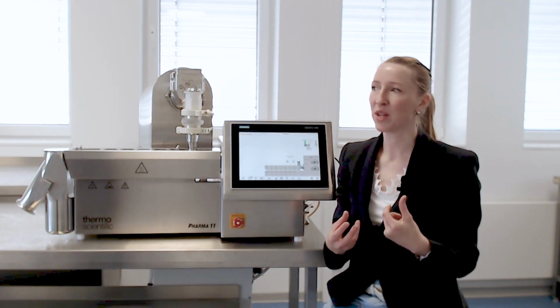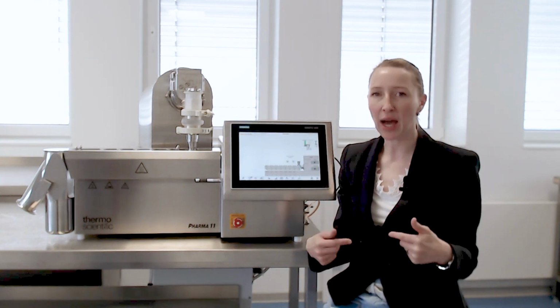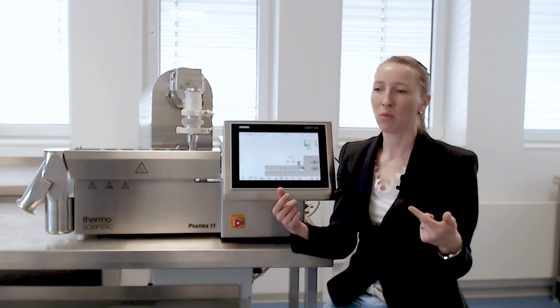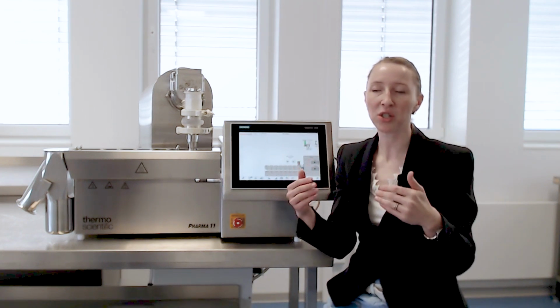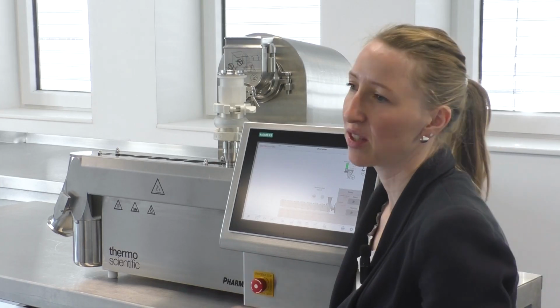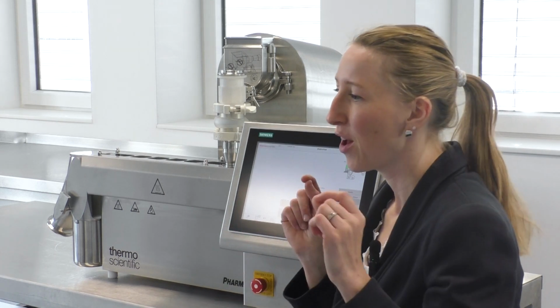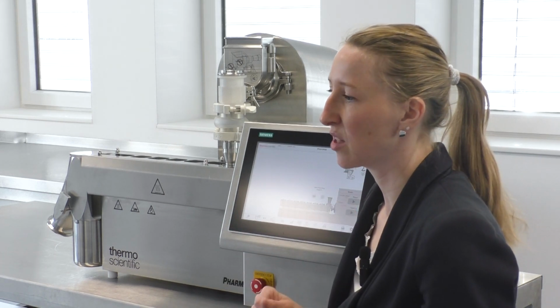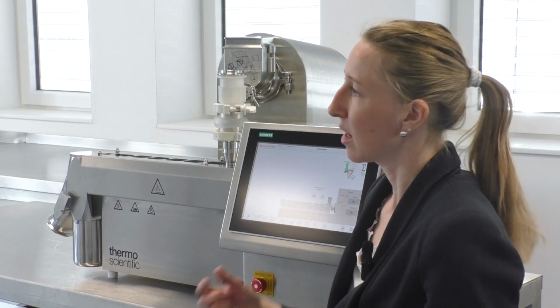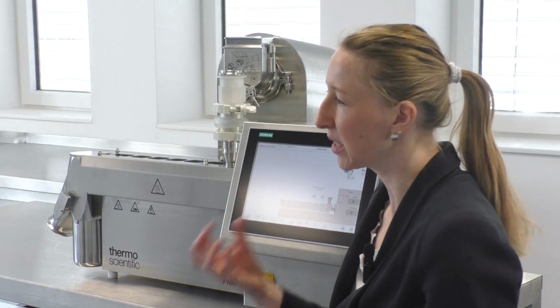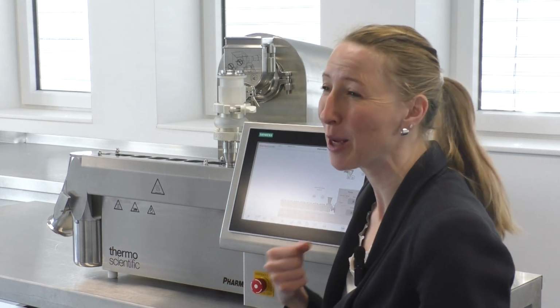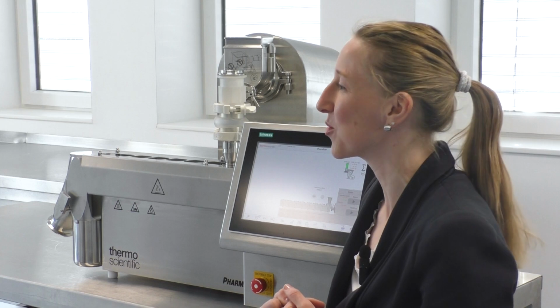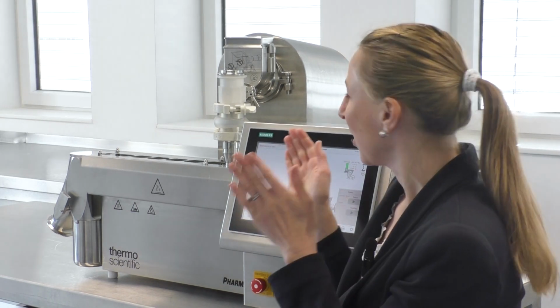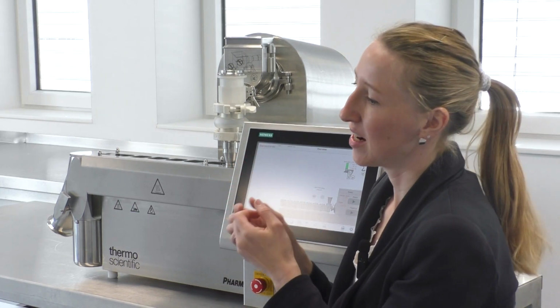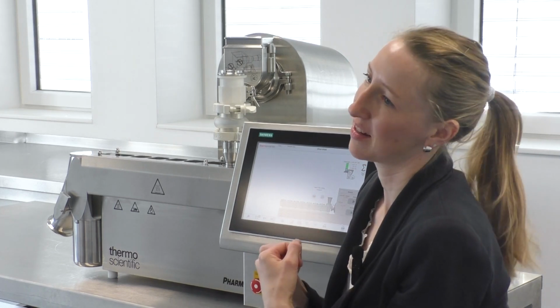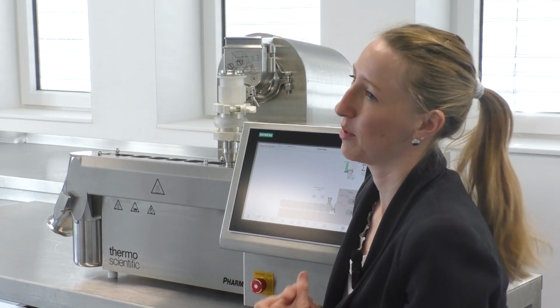The only thing that took a little bit of time and effort was to change the screw configuration, because what we found with this process, what is super crucial, is that you have the right screw configuration, and it has to be quite intense mixing and kneading, and quite some energy that we need to introduce into the process in order to reach enough energy to break down the crystals and to mill down the material.